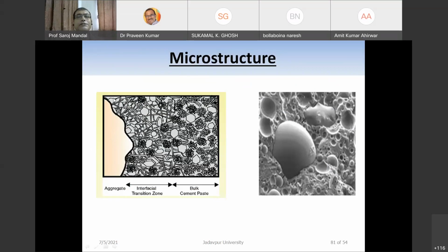And whenever any concrete fails, basically it fails along this boundary, right? That is the boundary of the aggregate, and this boundary and these zones we normally call the interfacial transition zone, ITZ. Why does it fail in the ITZ? You see here in the ITZ there is a lesser amount of this CSH gel. Mostly it is calcium hydroxide, and the calcium hydroxide structures are plate-like, and the behavior of these plates is that they are always perpendicular to the surface of the aggregate.